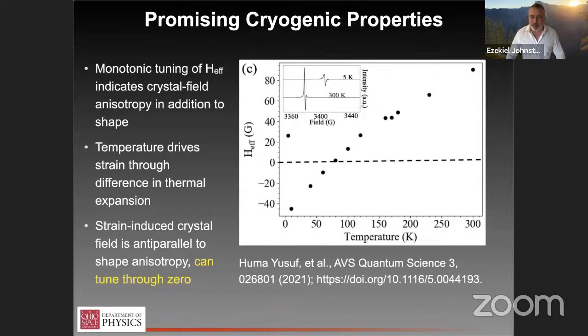But you have other systems with steeper M versus T curves where you would see a bigger effect. Here, what we're dominated by is not any intrinsic temperature effect, I would say. This is not formally the temperature affecting the magnetic resonance. It's the temperature affecting the strain, and then the strain affecting the magnetic resonance. So I think by far the dominant effect of this variation of over 100 Gauss, which is basically 100% or 125% tuning of M sub S, right? So we go from a positive to a negative value.